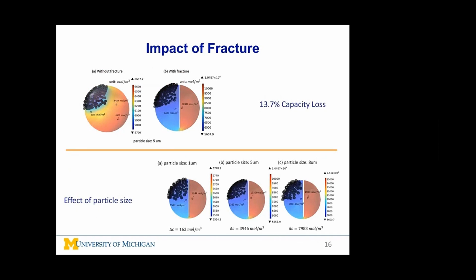When crack occurs in a particle, lithium will be trapped and cannot participate in intercalation or deintercalation. For instance, here we can observe a large difference of lithium concentration on the two sides of the crack. This reduces the usable capacity.